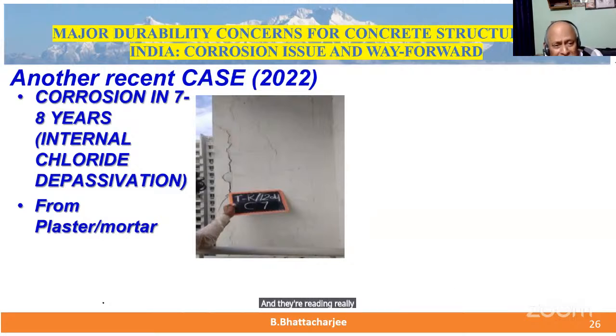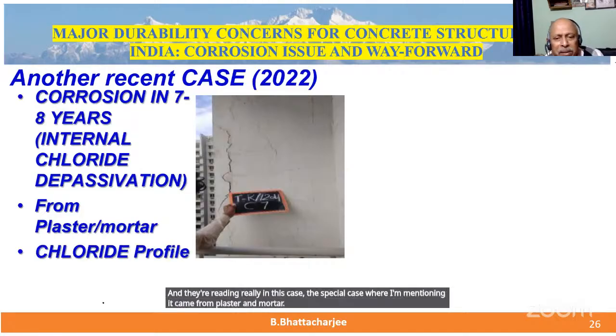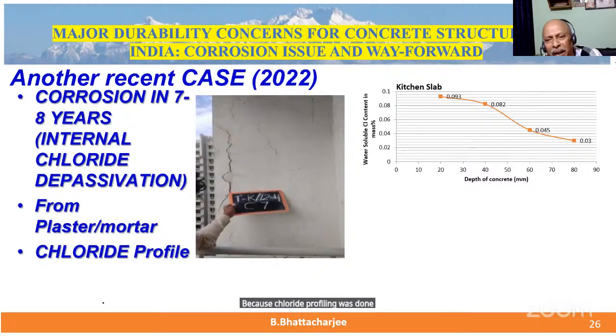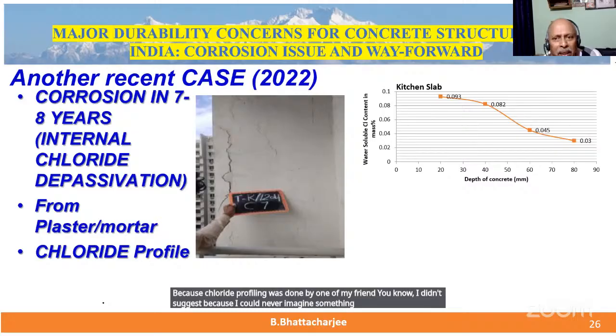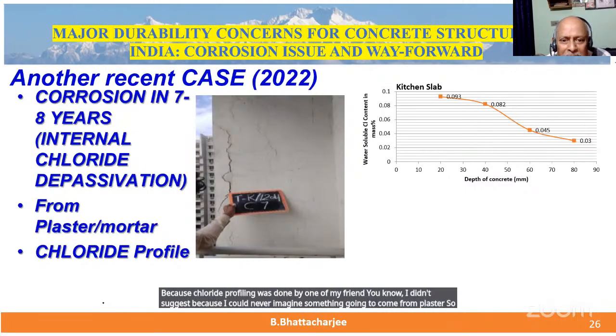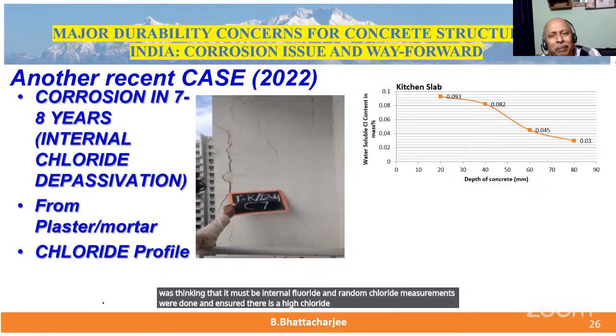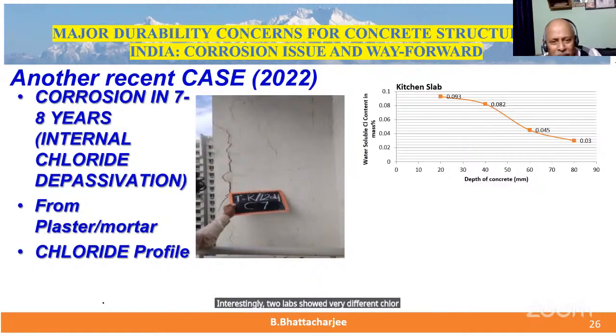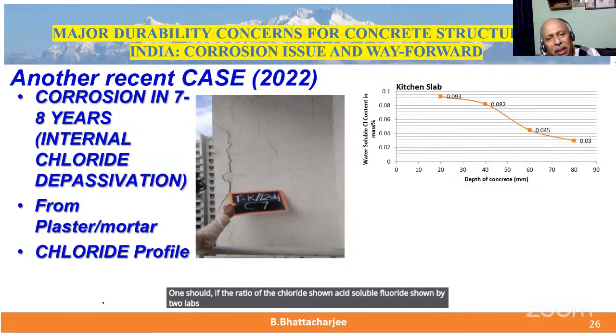In this case, the special case why I'm mentioning it came from plaster and mortar, right? Because chloride profiling was done by one of my friends. I didn't suggest because I could never imagine something can come from plaster. So I was thinking that it must be internal chloride, and random chloride measurements were done, and it showed there is a high chloride. Interestingly, 2 labs showed very different chloride before we took over. One showed the ratio of the acid soluble chloride shown by 2 labs, where 1:3. So one has to be very cautious about chloride testing.